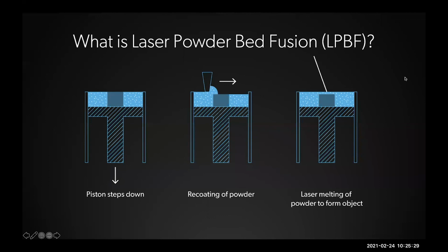So taking a step back, what is laser powder bed fusion? On a real high level, it is the accumulation of powder over layers fused together by a laser. And at the end of the day, these individual layers are stacked upon themselves to make a part. It consists primarily of a piston that moves inside a cylinder bore that moves down each consecutive layer. In our case, it's 50 microns, about 2/1000 of an inch.